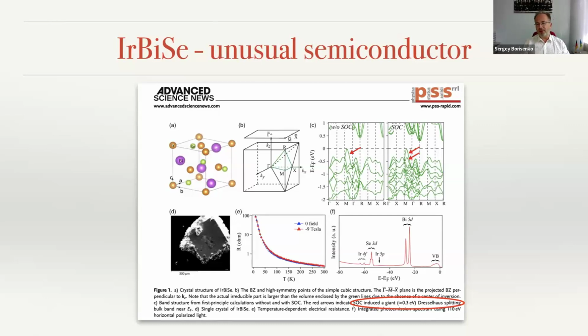But the very interesting feature, why we called it unusual semiconductor, is that we realized that there is a very huge splitting, at that time we called it gigantic Dresselhaus splitting, of sort of 0.3 electron volts. And for us, it was very important because this fully spin polarized band was nearly touching the Fermi level. So this is a semiconductor, but a tiny doping would make it a metal, and one could get extremely interesting Fermi surfaces, and I'm going to show you what this is.